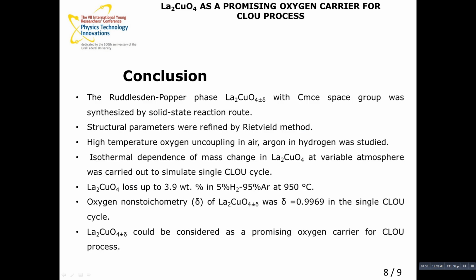As a result of the current study, it could be concluded that the Ruddlesden-Popper phase lanthanum cuprate has a number of desirable properties as an oxygen carrier in the CLOU process.